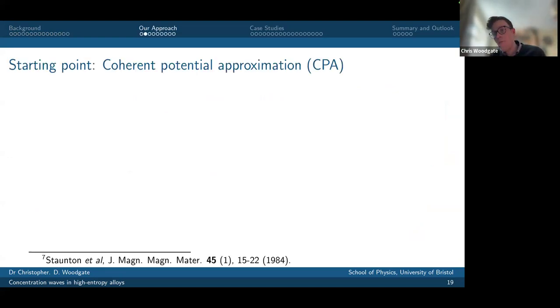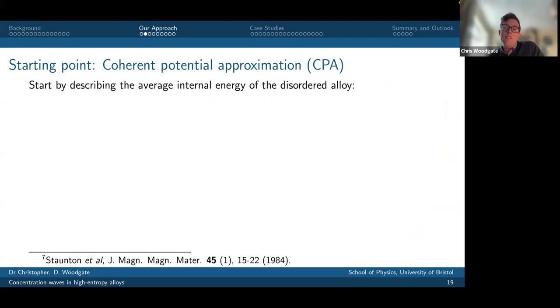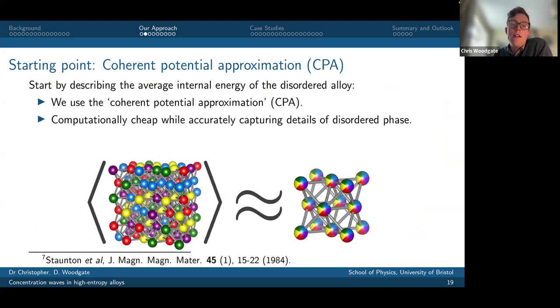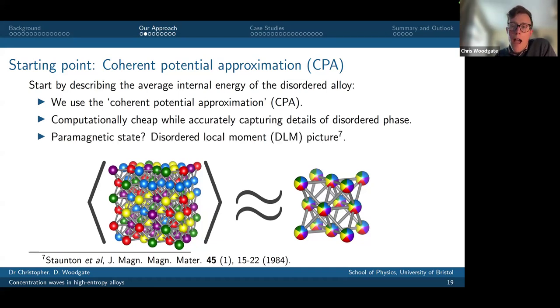So our starting point is to use the coherent potential approximation. Okay, so this is this well-known means in multiple scattering theory of describing the average electronic structure and consequently the internal energy of the disordered alloy. Okay, and the idea is that this is very computationally cheap because you can work with the primitive unit cell of the underlying lattice, but it turns out to accurately capture many details of the disordered alloy. And the beautiful thing is that if you want to simulate a material in its paramagnetic state, you can apply something known as the disordered local moment picture, which was pioneered by my PhD supervisor, among others, Julie Staunton, where you can consider averaging over many possible orientations of magnetic moments.